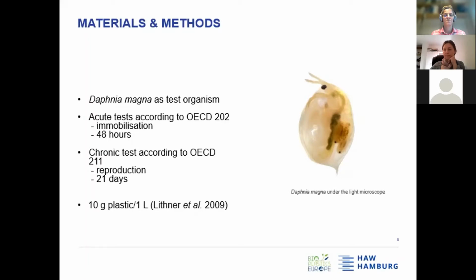In addition to acute testing, we also tested the bioplastic materials by chronic tests according to OECD 211. The test duration was 21 days for chronic testing, and the reproduction of the daphnids was observed. The plastic concentration was between 0 and 10 gram plastic per 1 liter medium. This is in accordance with the study of Lithner in 2009.